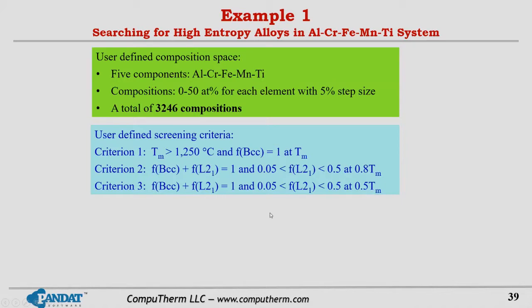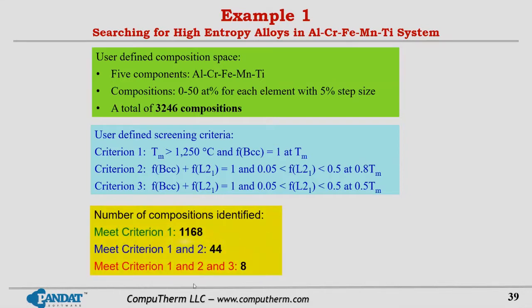From these criteria, we data mined the simulated results and found that the number of alloys meeting criterion one is 1,168 alloys. For alloy compositions meeting criteria one and two, we have 44 alloys. For compositions meeting all three requirements, we have only 8 alloys. So we down-selected from a total of about 3,200 alloys to 8 alloys for experimental validation.